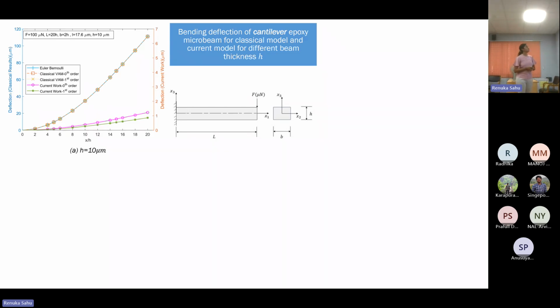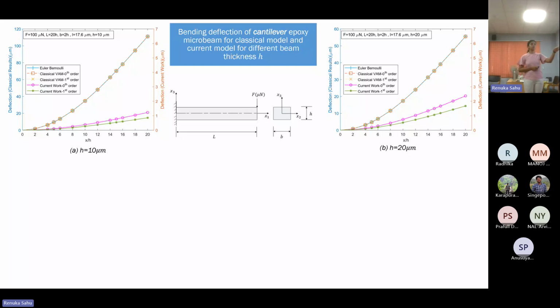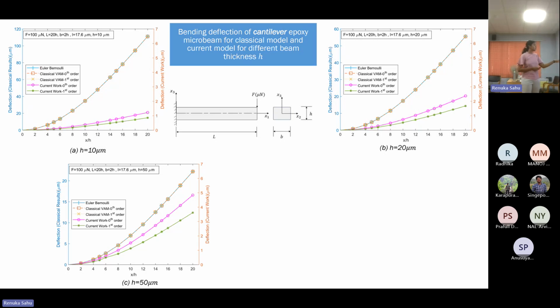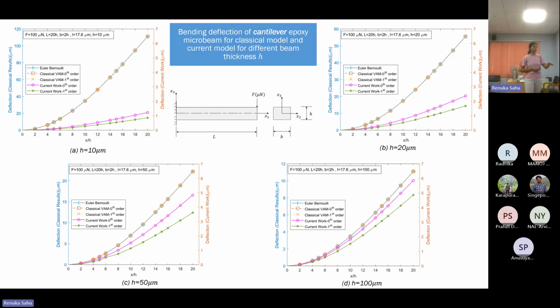For a thickness of 10 micrometers, the classical results give much higher bending deflection, while the current work, using the strain gradient model, gives lower bending deflection, showing that the beam has stiffened at micro scale. Similarly, at 20 micrometers thickness, the difference between classical and current work reduces, and as you keep increasing the thickness, the difference keeps on reducing.